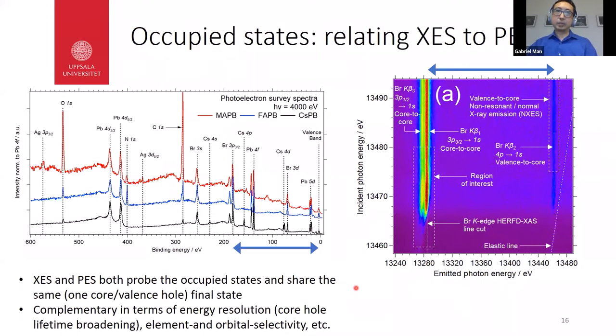This is a comparison between, on the left-hand side, photoelectron survey spectra, and on the right-hand side, the resonant X-ray emission map. The blue arrow here, in both cases, is intended to represent the same energy offset, which is between the valence band and the bromine 3p core level.